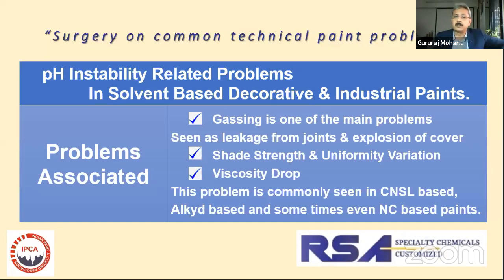Certain other subtle problems are also happening. That is, your shade strength is lost, the uniformity in the shade development is lost, there's a viscosity drop, and as I said, if you have added water, the stability of the water in your system is again questionable if the pH is not stable. This problem is very commonly seen in your CNSL-based paints, alkyd-based paints, and some people have reported to me with NC-based paints also, the gassing, the leakage complaint.